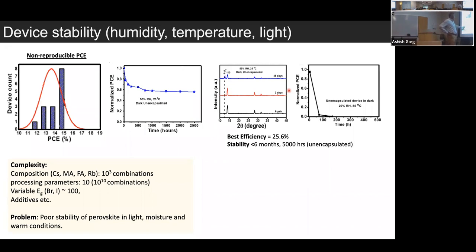But the problem is, if you look at compositions of perovskites, you have cesium, methyl ammonium, formamidinium, rubidium, and so forth. There are at least 1,000 combinations to try, which is not a trivial job. Similarly, if you look at processing parameters, there are at least 10 processing parameters, which give you nearly 10 to the power 10 combinations. So it's physically not possible to screen out everything.